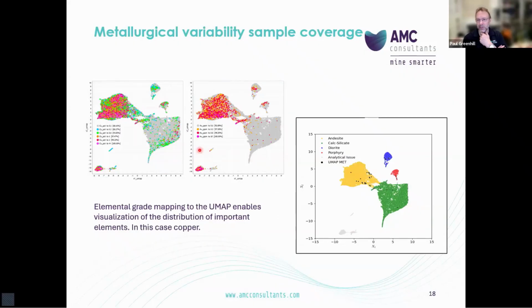Now, as I've said before, because the data includes all the characteristics of samples, we can select any of these to plot on the UMAP. And what we've got here is the elemental grade mapping for another deposit, for copper and for gold. And again, hot colours represent high grades. So this allows us to work out specifically in this instance whether we in fact sufficiently covered the grade variation for copper or gold with respect to metallurgical testing.